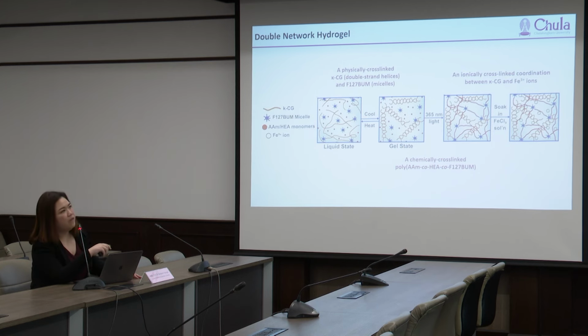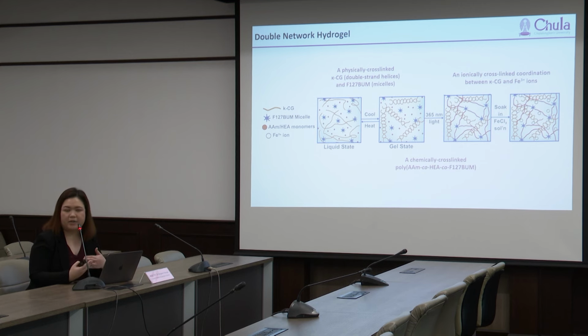So if you look at this network, you can see that we have a lot of cross-links in the network. The first one is the physical cross-link from the double helix of the kappa carrageenan and also the micelle structure from the F127. We also have the chemically cross-linked network from the monomer and the cross-linker. We also have the ionic cross-link coordination between the sulfate of the kappa carrageenan and the iron here. So from this cross-linked network, it can improve the mechanical property of our hydrogel significantly.